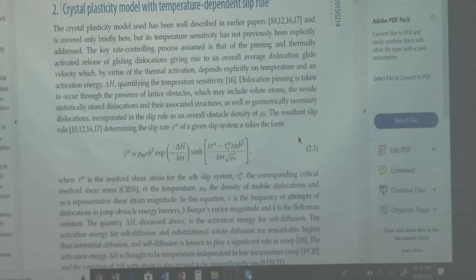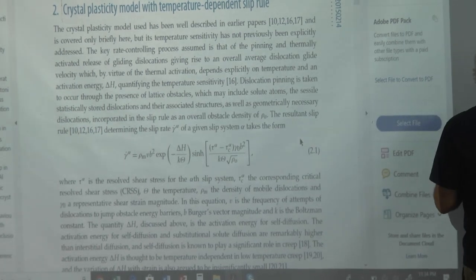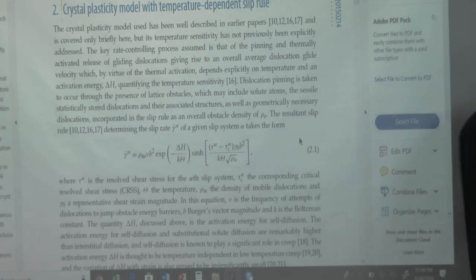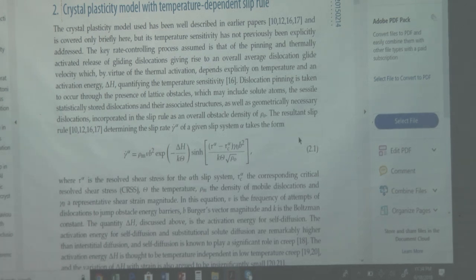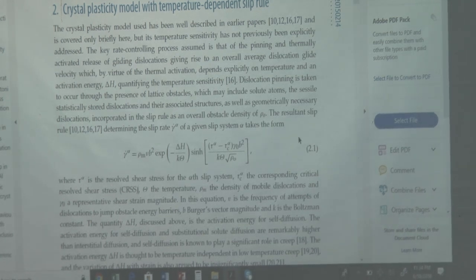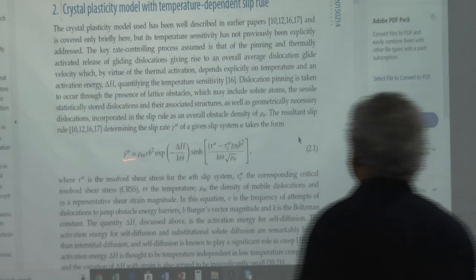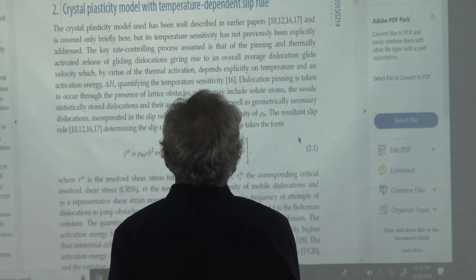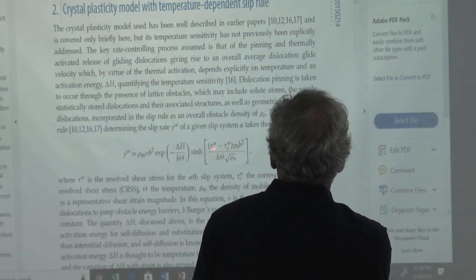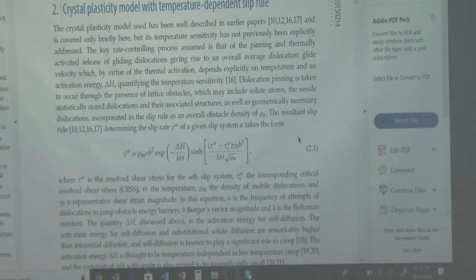You remember the equation? There is an equation, that is the mobile dislocation density equation. Rho m b v, epsilon dot is equal to... There are two shear stresses in the equation. One is the resolved shear stress. One more is the critically resolved shear stress, CRSS. Well, one is critical, one is not critical.